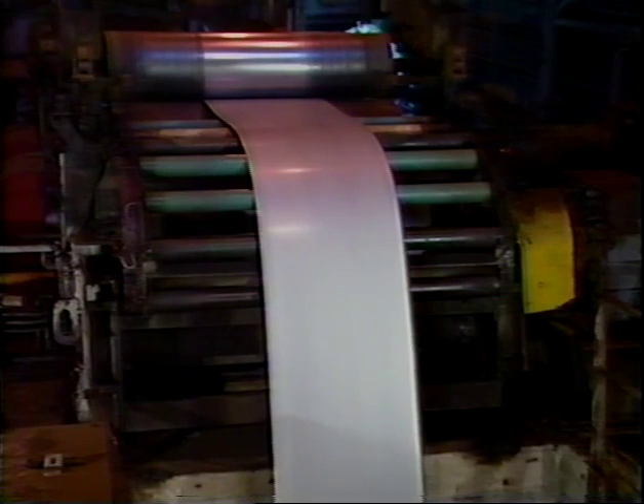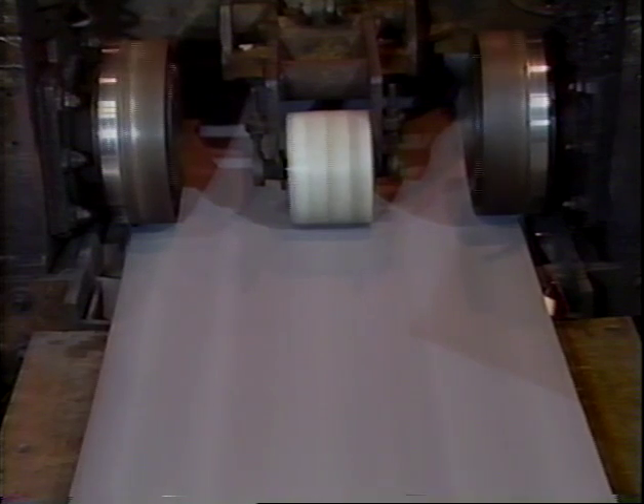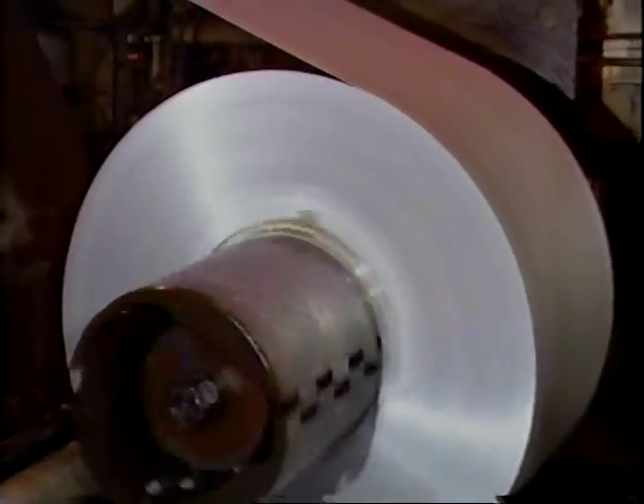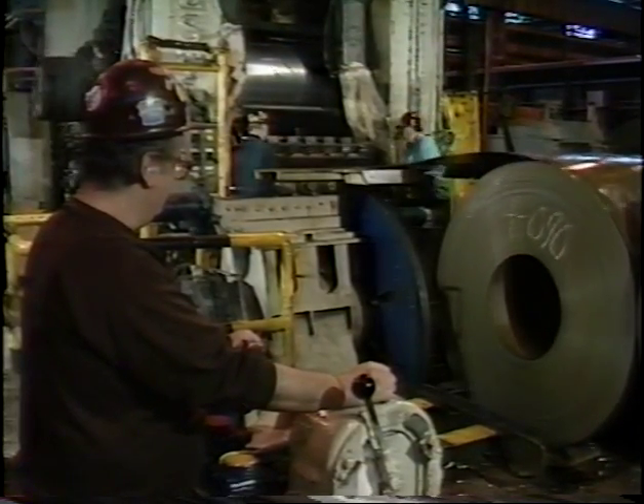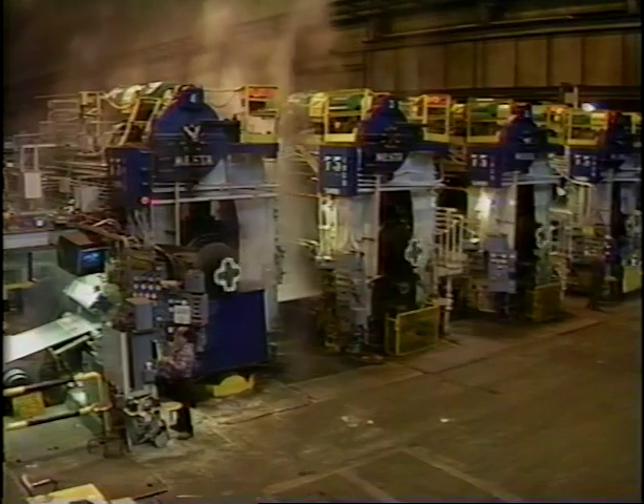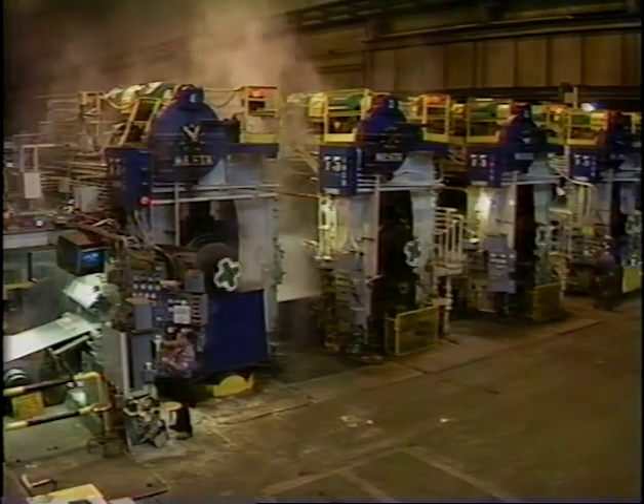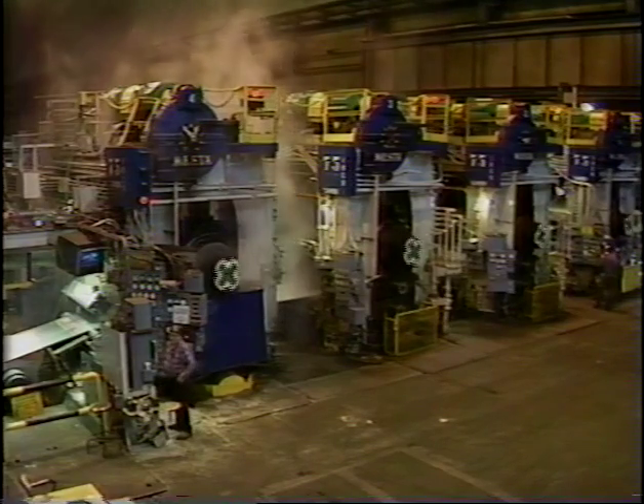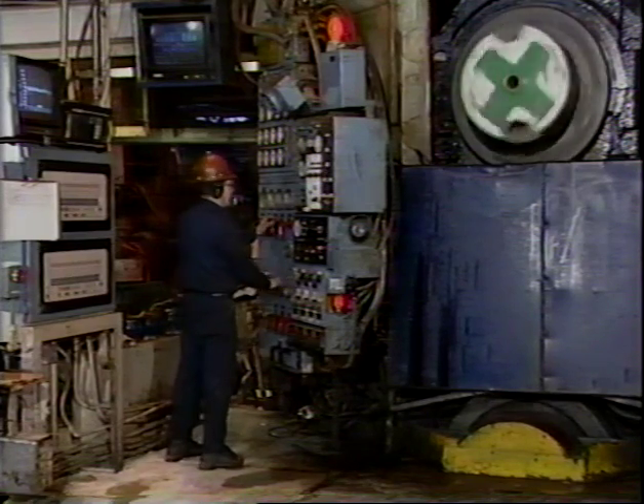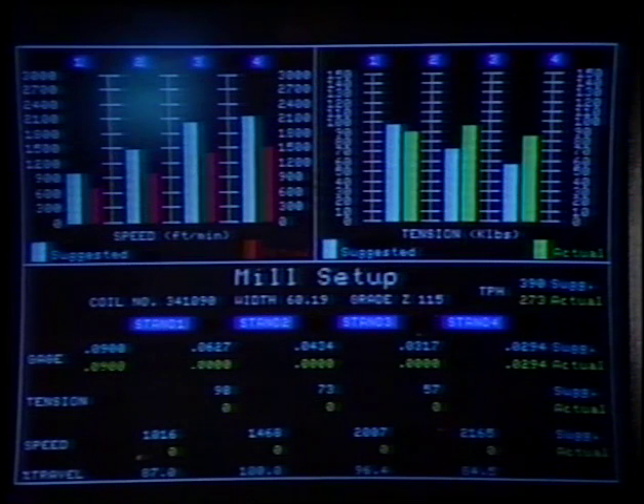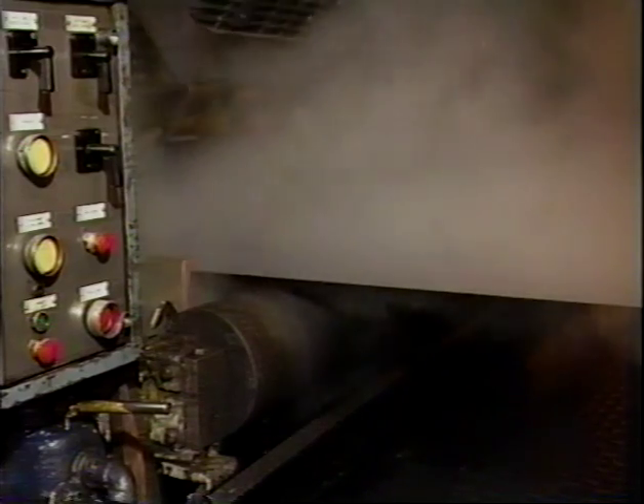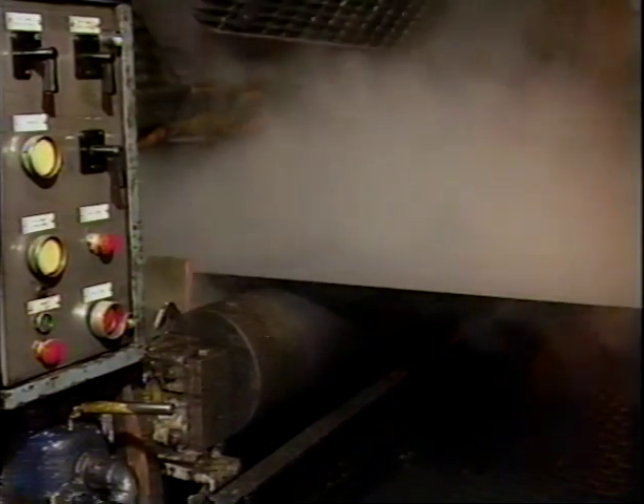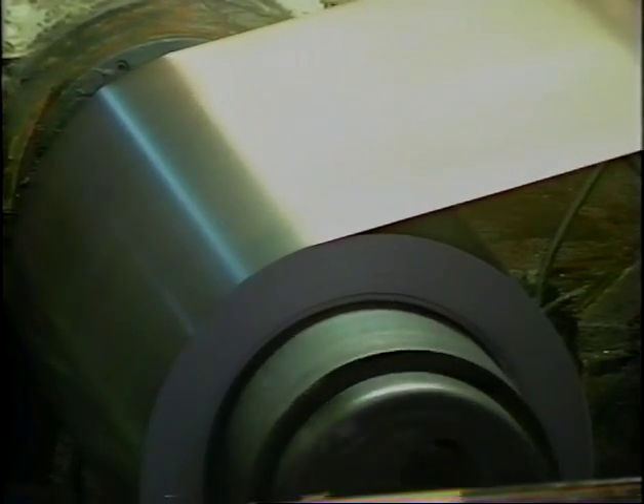Clean steel emerges at the delivery end of the pickler. It's slit to width and wound to the customer's specified maximum coil weight. Clean coils from the pickler move to the four-stand tandem mill, where they're reduced to the customer's ordered thickness. We do it quickly, and we do it accurately. Computer-generated mill presets, feed-forward automatic gauge control, and X-ray gauges let us guarantee half-standard tolerances. Roll bending and a water header shape control system help us produce a very flat sheet.